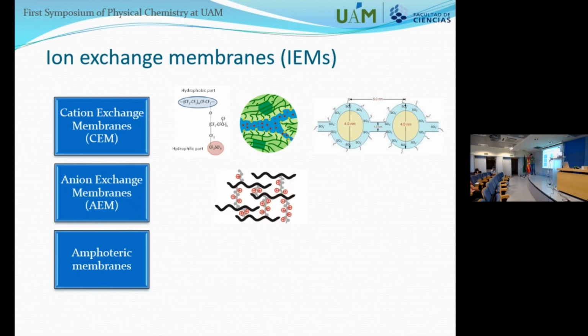If we go to the anion exchange membranes, we have the opposite. We have positive charges fixed in the structure, and that helps for the conduction of negative ions. And this has also an advantage, talking about the vanadium redox flow battery, which is the Donnan exclusion effect, which is based on the electrostatic repulsion of the vanadium ions, since they have positive charge. And we also have positive charges inside of the membrane. The positive ions are repelled and they don't tend to go through the membrane. So these membranes, opposite to the previous ones, usually have a better barrier to the positive ions. This is one of the reasons that they are being quite investigated for vanadium and other redox flow batteries that have positive ions.